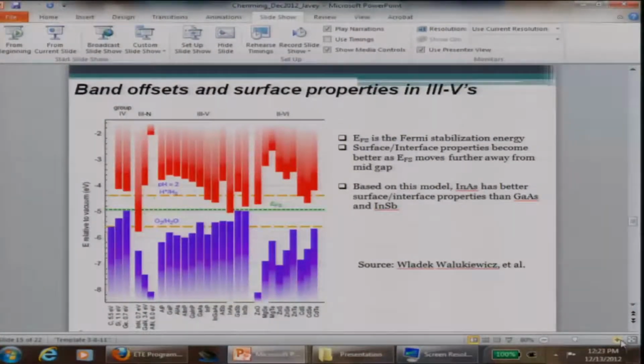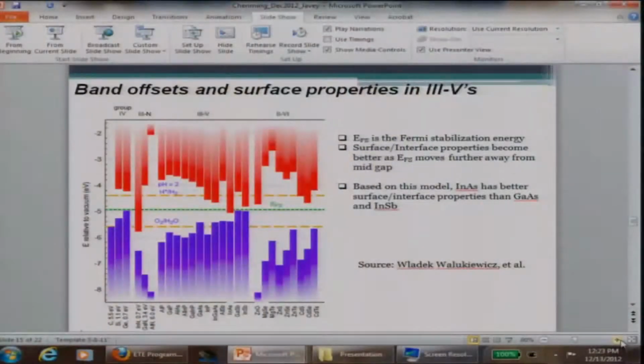We are exposing it to different etchants. We are exposing it to different polymeric materials, organic materials, and yet we're getting pretty good Dits, pretty good subthreshold swings. So what is so magical about indium arsenide? This is a nice chart that summarizes the conduction band edge, shown in red, and the valence band edge, shown in blue, for different semiconductors. So great, from this you can see the conduction band, the valence band, their location, the band gap, and all that.